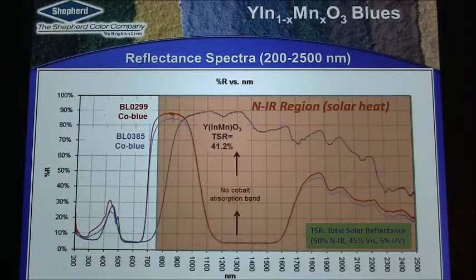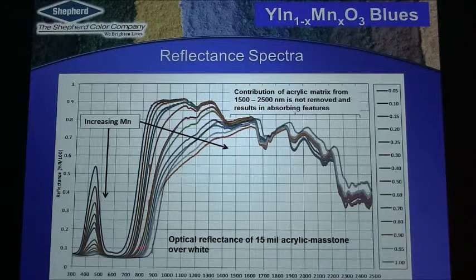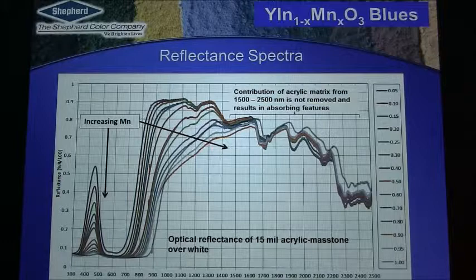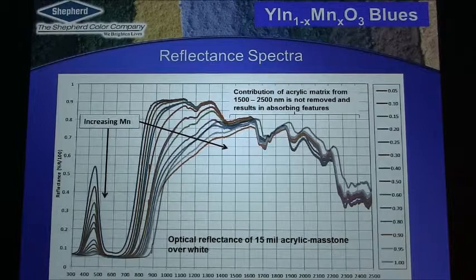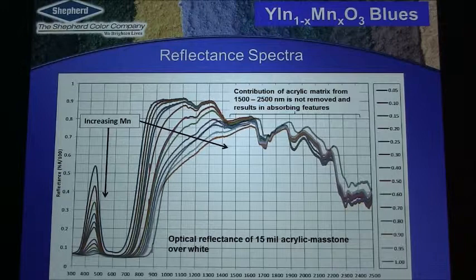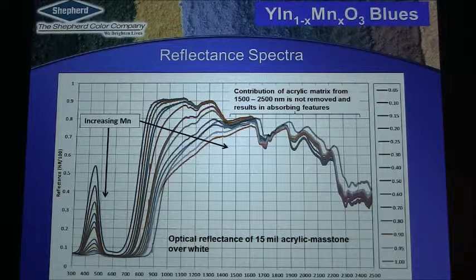In fact, our pigment can be tuned, because when you have a high manganese content, the solar radiation reflection decreases. So the presence of the indium is very helpful in getting the solar reflectance very high actually. So definitely, not only the color of this pigment, but its durability as well as the infrared reflection is very important to make this pigment very interesting for many applications. So we call them multifunctional pigments.